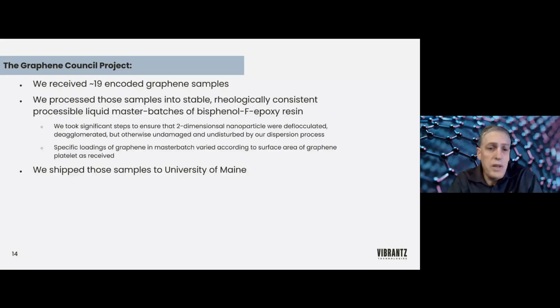So what we did was we took these different unidentified encoded samples and we processed them into stable, rheologically consistent, processable liquid master batches that we thought that University of Maine would be able to handle. In the process of doing that, we took a lot of care. Not knowing what these particles were exactly, we tried to process them all under the same conditions, understanding, of course, that they were different materials and had to be handled a little bit differently. So we went to a lot of work to make sure that two-dimensional particles were deflocculated and deagglomerated, but otherwise undamaged and undisturbed by our dispersion process.